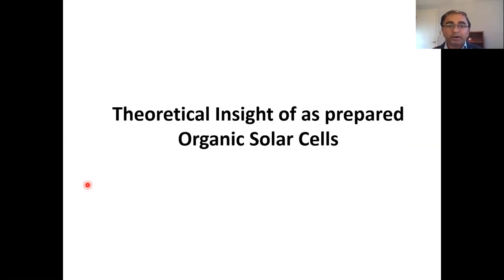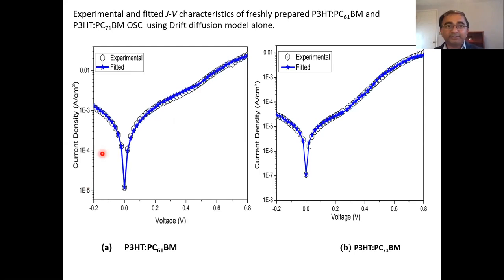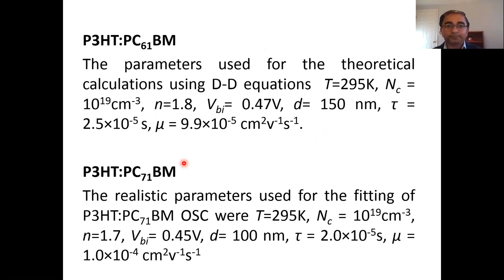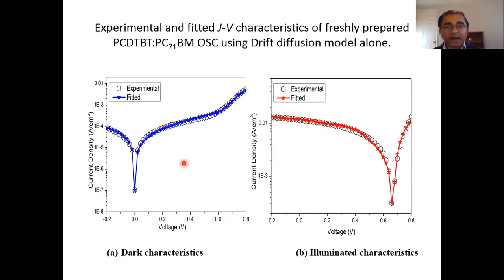And using these two models, what we observed is that for P3HT devices, the drift diffusion model alone is required to understand the current conduction phenomena in these devices. So these are the optimized parameters used in the modeling. And for PCDTBT, again, we used to fit the drift diffusion model, and we observed that the drift diffusion model alone is sufficient to understand the current conduction phenomena in these devices.